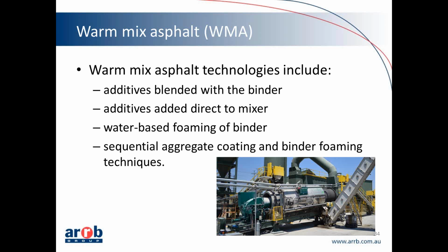People came along with other additives that could be added direct into the asphalt mixer, and then people found that simply by using water to foam the asphalt, it changed the way in which the binder could coat the aggregates at lower temperatures and also improve the placing. And then there's also the proprietary process that involves a sequential aggregate coating and binder foam technique, but it does require a special mixing plant.